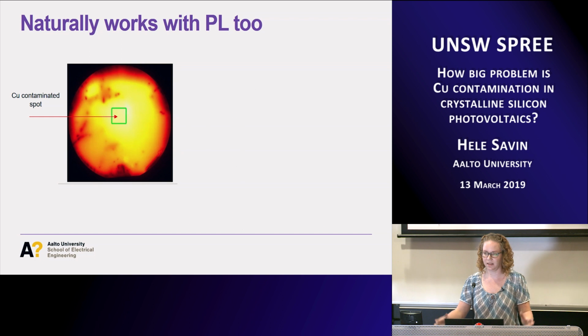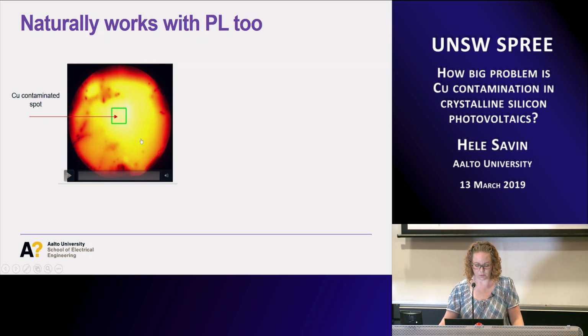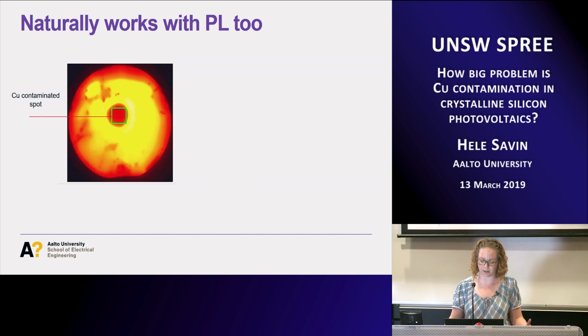About photoluminescence, of course, it has much higher spatial resolution, and it's much faster than the methods we have used in the past, micro-PCD for instance. So this is just to demonstrate that in photoluminescence we should see the same thing. Initially we have placed copper in this location here, and if you do a PL map, you don't see anything because you're not supposed to see anything. But when you start illuminating your wafers, putting some light soaking into it, you should start seeing what happens. So the copper LID really appears there, as was expected.